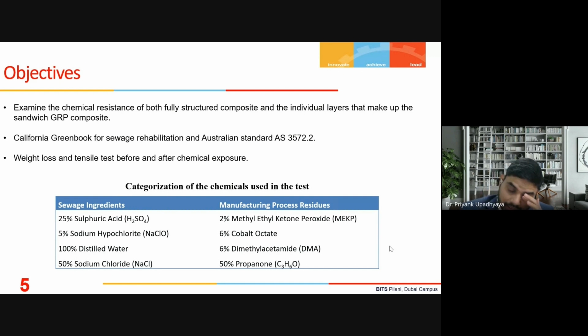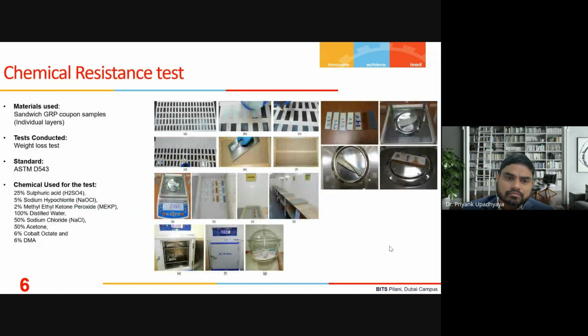And these chemicals are MEKP. MEKP is a curing agent. Then we have Cobalt Octate, which is used as a catalyst. And then we have DMA. DMA is an accelerator that is used to speed up the reaction that's coming from the Cobalt Octate. And then we have acetone. Acetone is used mostly for cleaning purposes, and you will see how bad this acetone could be from the chemical exposure perspective. So now what we do in this, we prepare the samples using conventional molding process.